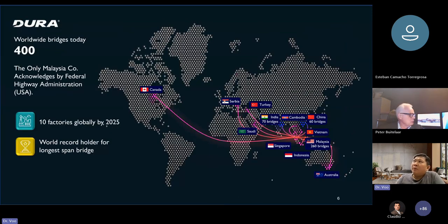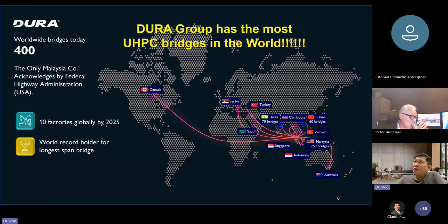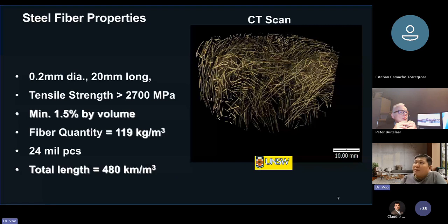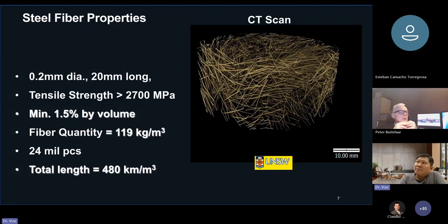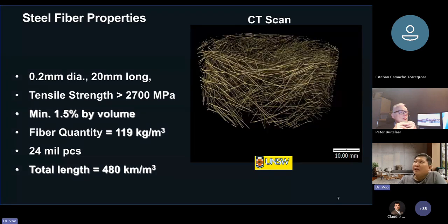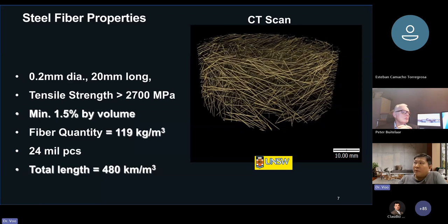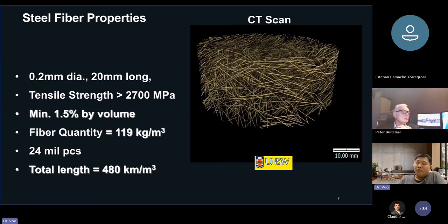By now we have constructed about 400 UHPC bridges in Malaysia, China, and India. In Malaysia alone, the latest number I have is that we have so far done about 260 UHPC bridges, from small scale up to quite a large span. The UHPC we produce generally uses only one type of fiber. Our UHPC has about 1.5% by volume of steel fiber, and the size is 0.2 millimeters in diameter and 20 millimeters in length. The fiber content is about 119 kg per cubic meter.